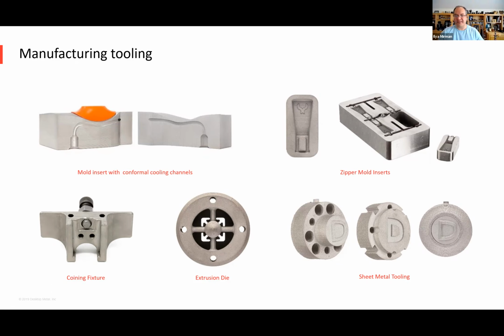So you see this first example of a mold insert with a conformal cooling channel. So this is the part that's actually getting molded. We printed this part just halfway. So you see there's an internal cooling channel. The big win there is you can dramatically decrease the cycle time. The cooling time decreases, and so you can dramatically increase the frequency with which you're molding these parts.